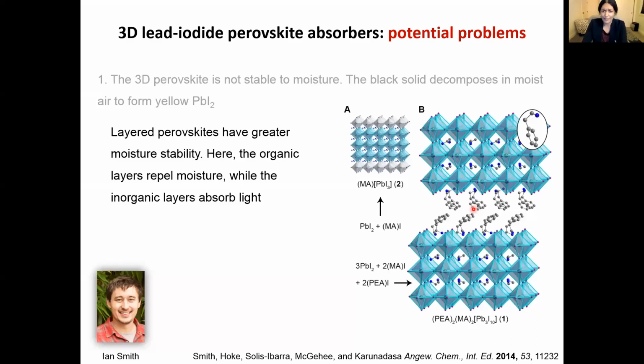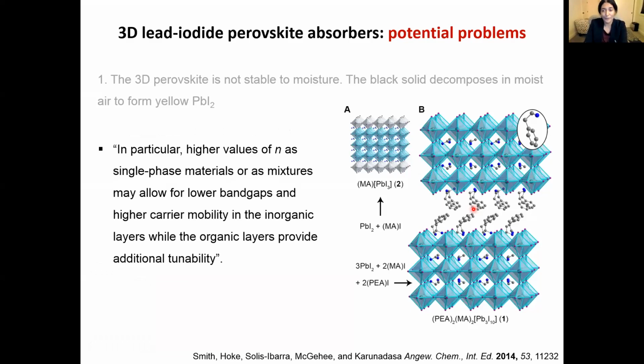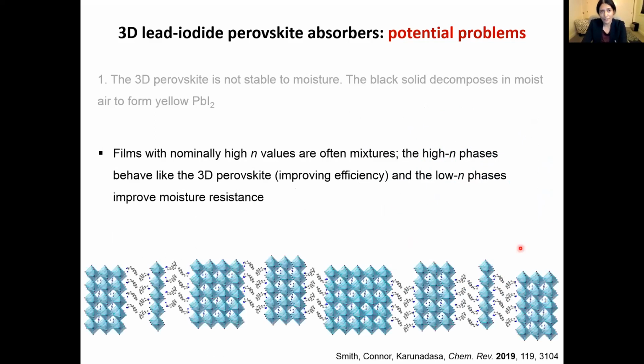And in our first report, we had a device efficiency of, I forget, something like 4-point-something%. But since then, the device efficiencies of 2D perovskites have also rapidly risen as more and more groups around the world have been looking at 2D perovskite solar absorbers. So we ended this first report by saying that as you increase n, which is the number of layers in the inorganic layers, so this is n equals 3, we predicted that as n gets larger and larger, even if you have a single phase material or even if you have a mixture, you will get higher and higher device efficiency as n increases, while the organic layers can still provide moisture resistance. And this is exactly how the field has progressed. And efficiencies of 2D perovskite solar cells are now rising.